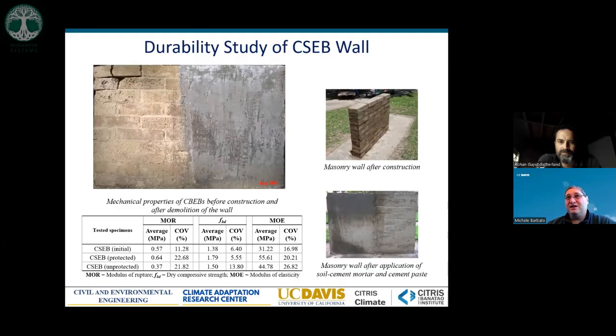unprotected, started rapidly degrading. What happened there was that the heavy rain was washing away the mortar. The mortar doesn't have the same compaction properties that were provided to the bricks, and so tends to be washed away more rapidly by the rain that penetrates across the joints. And then when enough mortar was washed away, the top brick fundamentally became a cantilever brick. And then I imagine, even though we had signs saying people don't sit on it, don't touch it, and all of that, probably some students decided to sit on it and broke the block that you see on the top. Anyway, it's not really the type of performance that you want for a wall, even under heavy rain.